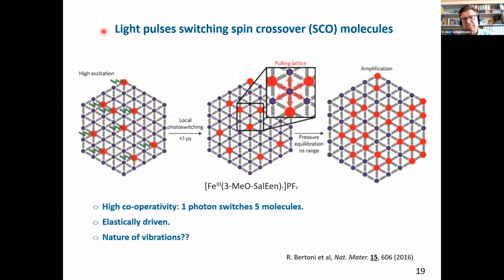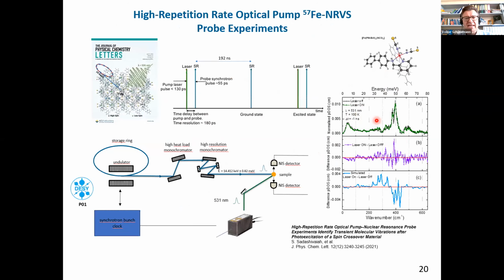There was recently, some years ago, a paper which suggested that after light excitations of these S equals 2 states, you have amplifications of the high spin state in these systems driven by phonons in the nanosecond range. And that motivated us to perform high repetition optical pump, iron 57 NRVS probe experiments with the laser, short delay time before the synchrotron pulse. By that time, we had a time resolution of 1 nanosecond. Now we can have time resolution even at 150 picoseconds.